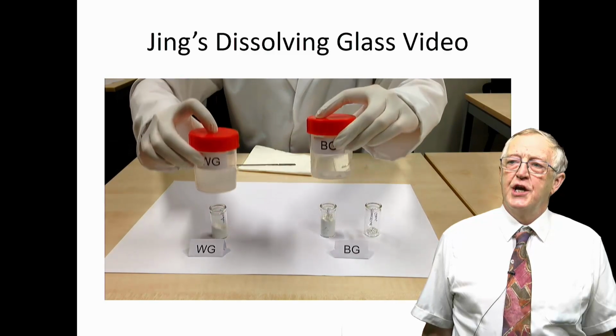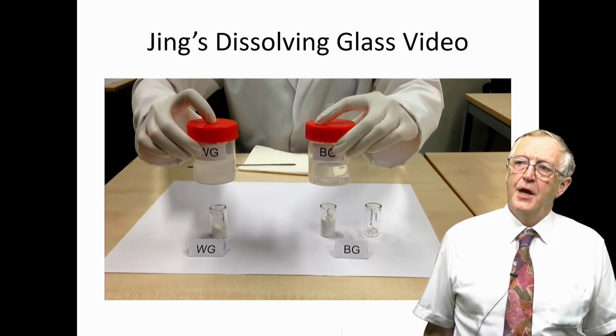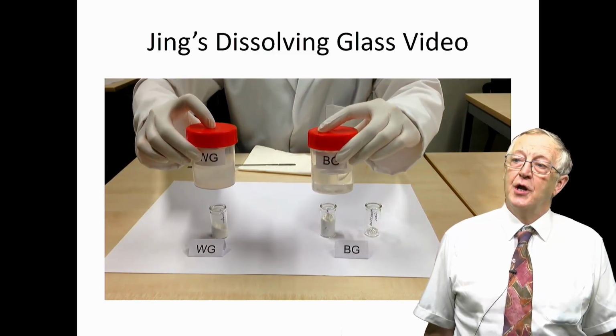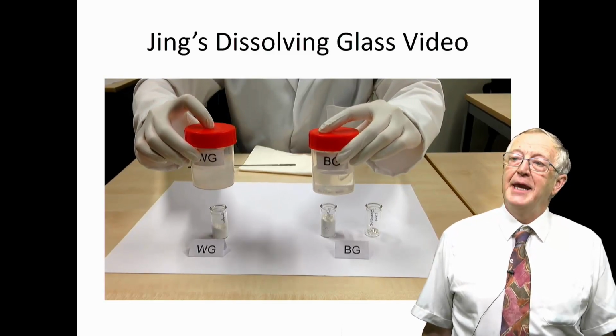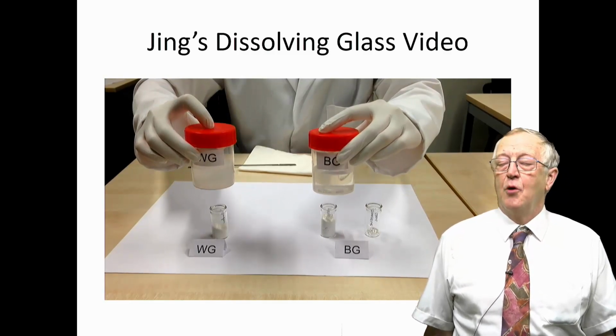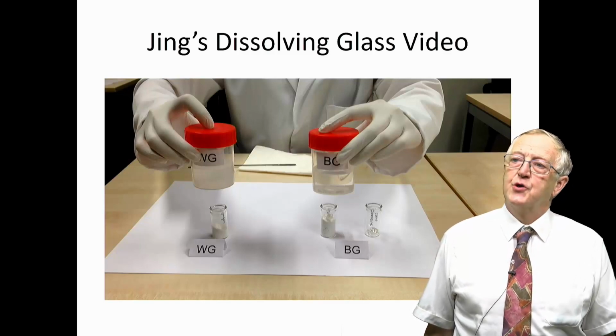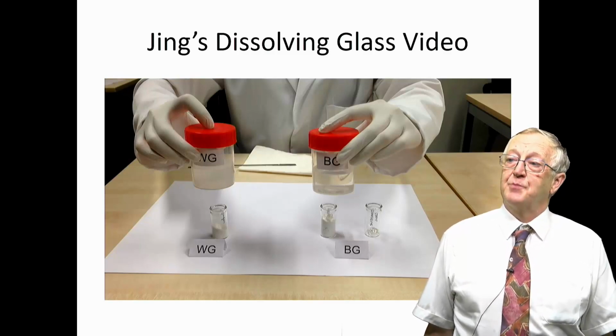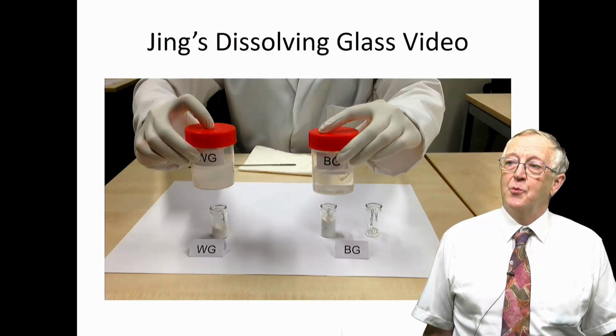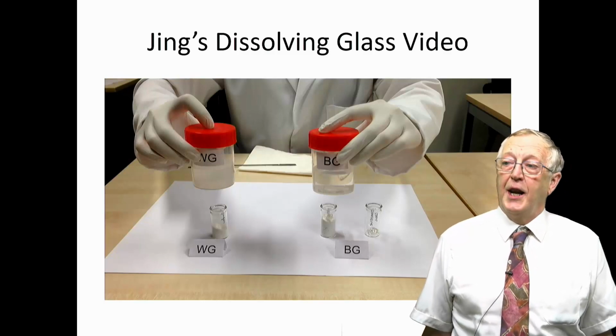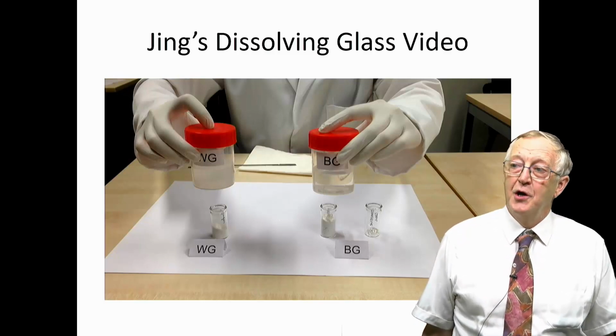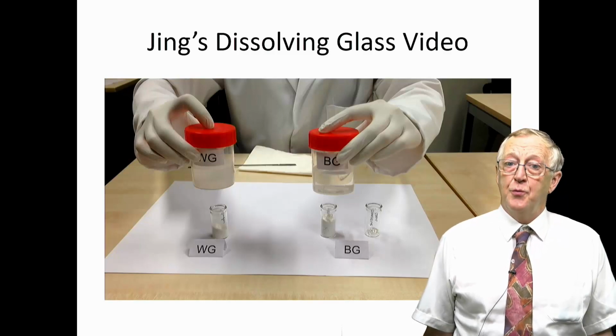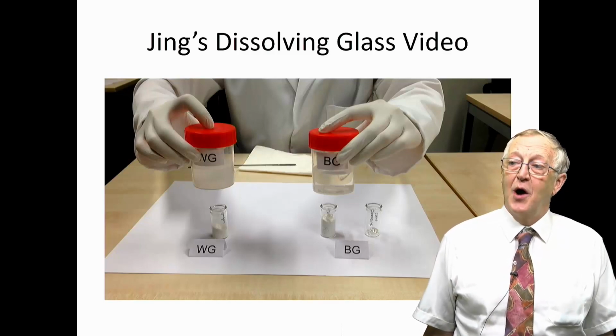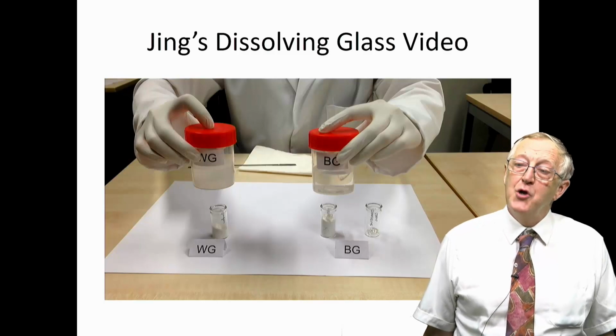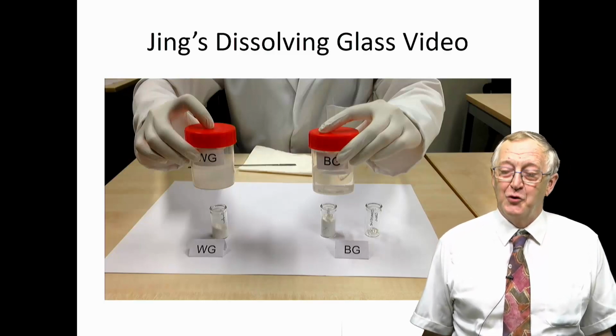And what you'll see when she holds them up to the light is the bioglass is a clear solution. It's dissolved completely in just probably 30 or 40 seconds, whereas the window glass has formed a cloudy suspension. Now, the glass that we produced for this video actually dissolves far too quickly for any practical use. The one we actually use in the toothpaste takes 10 to 12 hours to dissolve. But you wouldn't want to be watching this video for 10 or 12 hours.